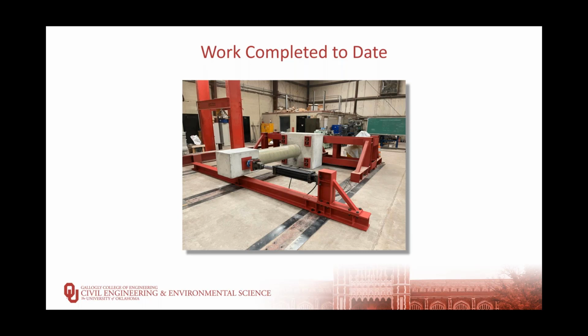The loading sequence consists of cyclic loading, where we start off with a set displacement, pushing it and then pulling it twice, 2 cycles for each increment, and then the subsequent increment is increased by 40%, and we do that until we reach a nice hysteresis loop for the column and then eventual failure of the column.